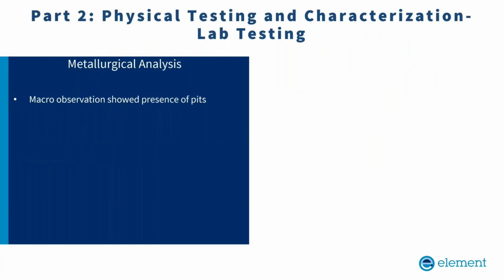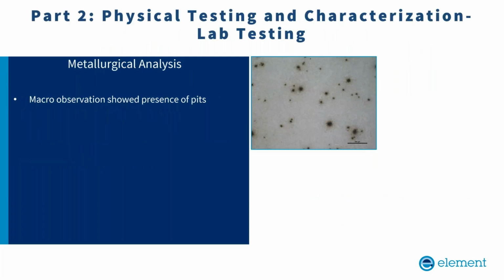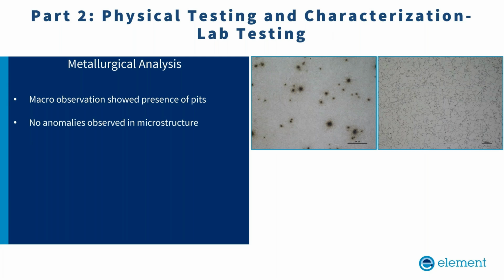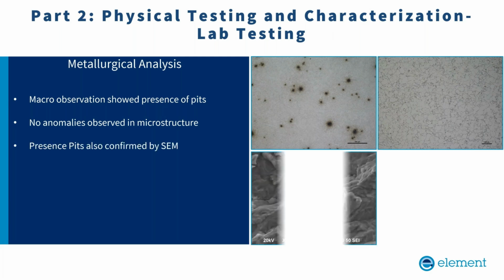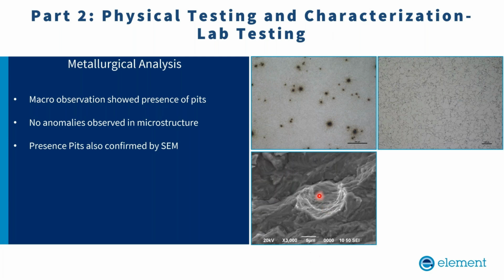So we have done an extensive in-lab microstructural analysis. There were no anomalies found in the microstructure. However, pits were observed in the microstructure, and they were observed during SEM observation as well.